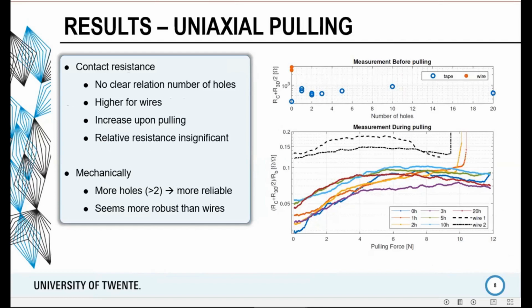Then for the pulling, from 0 to 12 newtons, you could see that initially there's a rise in contact resistance, which then seems to become stable, and after a while sometimes even goes down. For the samples with only 0, 1, or 2 holes, for a certain force, our contact would break. For more holes, they would stay intact, whereas the wires would also break around these values.